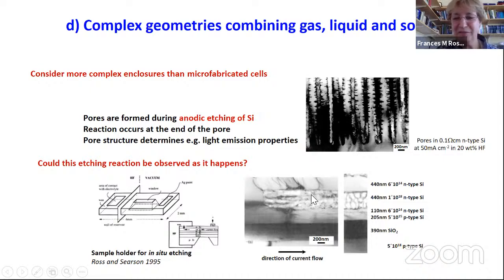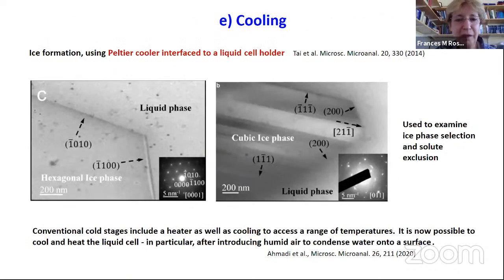The experiments didn't really work, but this was one of the things that got us thinking about assembling a liquid cell to put the electrolyte in. But really, there's no reason not to do this type of experiment using other materials where they form their own encapsulation. And then finally, cooling. We talked about heating. You can do cooling of liquids using small Peltier coolers, and you can thereby replicate some of the capabilities of environmental SEM in terms of condensing water. And this, I think, is very important for things like corrosion processes, which do take place in a water-air environment, and you want to condense the water out of the humid air.